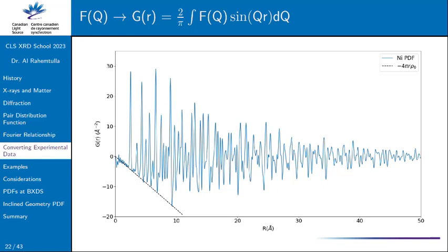Now that's the first neighbor. The second neighbor is a bit farther away, at 3 something radius, right? And you can find 3. You're going to have another peak there of height 3, and so on. So that's the pair distribution function, the histogram, the distribution of your neighbors per distance. I'm going a bit deeper on that. Let me page down.